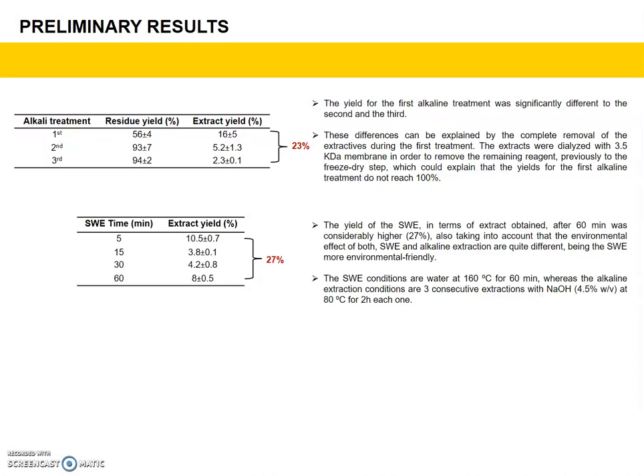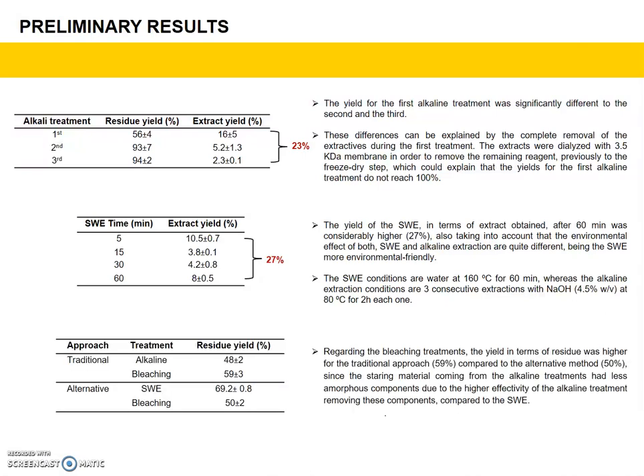Since the subcritical water extraction conditions are water at 160 degrees for 60 minutes, whereas the alkali extraction conditions are 3 consecutive extractions with sodium hydroxide 4.5% at 80 degrees for 2 hours each one. Regarding the bleaching treatments, the yield in terms of residue was higher for the traditional approach compared to the alternative method, since the starting material coming from the alkali treatment had fewer amorphous components due to their higher effectivity removing these components compared to the subcritical water extraction.